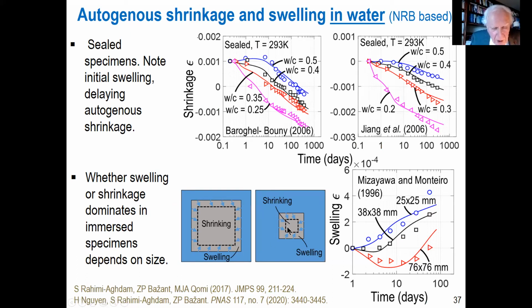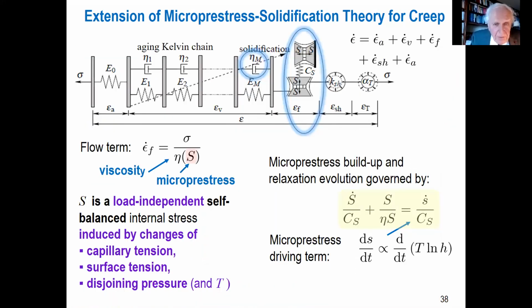In a small specimen, in water, it's obvious there is no longer an autogenous shrinkage part with solidification. Water penetrates in, there will be no solidification, and then you get the swelling. So without this assumption of expansion, you cannot model these data for the same concrete.